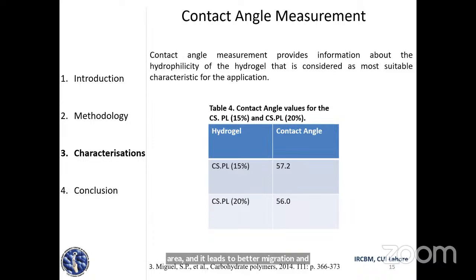A good angle is considered between 40 to 90, and our composite has shown a contact angle within it. The 15% hydrogel has shown a contact angle of 57.2, and the other with 20% hydrogel containing the active ingredient has shown a contact angle of 56.